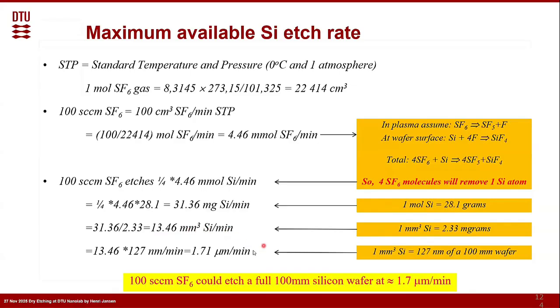And the final piece is that we know it's a 100 millimeter wafer. It's a circle, so we know the area. That means that we have to divide it by the area to know how much is the etch rate in depth. If you fill in that number, it is 1.7 micrometers per minute. So 100 SCCM of SF6 can etch a full 100 millimeter silicon wafer at 1.7 micrometers per minute if our assumption is correct. So if this is true, this is the best we can do. We cannot go faster because we don't have more SF6 available. We just don't have it. So this is following this rule.